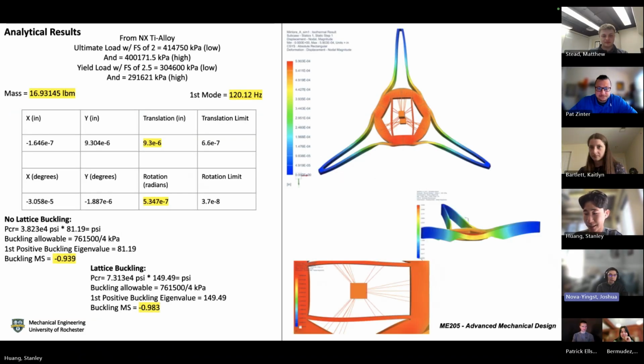For our final design, mass is 16.9 pounds, first mode of vibration just over 120 hertz. The translational displacement is about 9.3 microinches, and rotational displacement is 0.53 microradians, so off by more than a factor of 10. The buckling modes for both with and without the lattice hover at around -0.9.